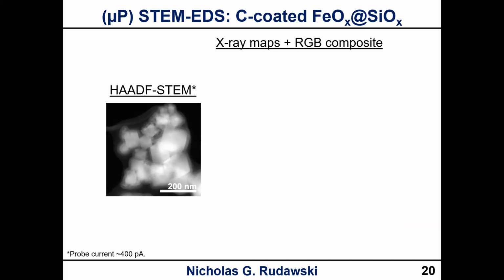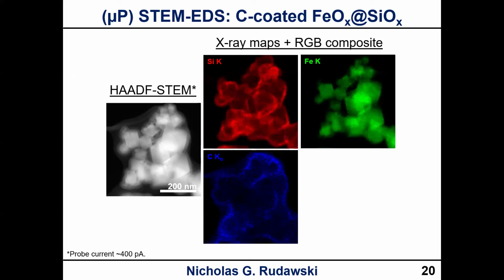If we look at something a little finer, so we've got these organic coated magnetite particles that also have a silica coating. There's your HAADF-STEM image. Again, this is with microprobe STEM. Our current is a lot less, though. It's about one third of what we had previously in the last example. Okay. But the advantage, again, we have like one of these.